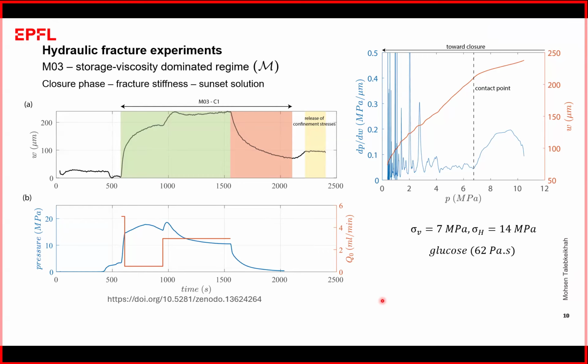First off, really impressive. I've never seen a work quite this sophisticated on this topic. I wonder if you're going to do this in low permeability formations, because if I understand it correctly, I think the sunset solution assumes that there is no leak-off from the parts of the fractures that are closed. And my expectation would be that in low permeability, the closed parts of the fractures remain at high dimensionless conductivity because the permeability is so low. And so leak-off would continue to occur from the closed parts of the fractures. So if I understand that correctly, and maybe I misunderstand the solution, I would wonder if it would not match low permeability data. And my related question is, does the sunset solution account for this residual aperture that you are showing?